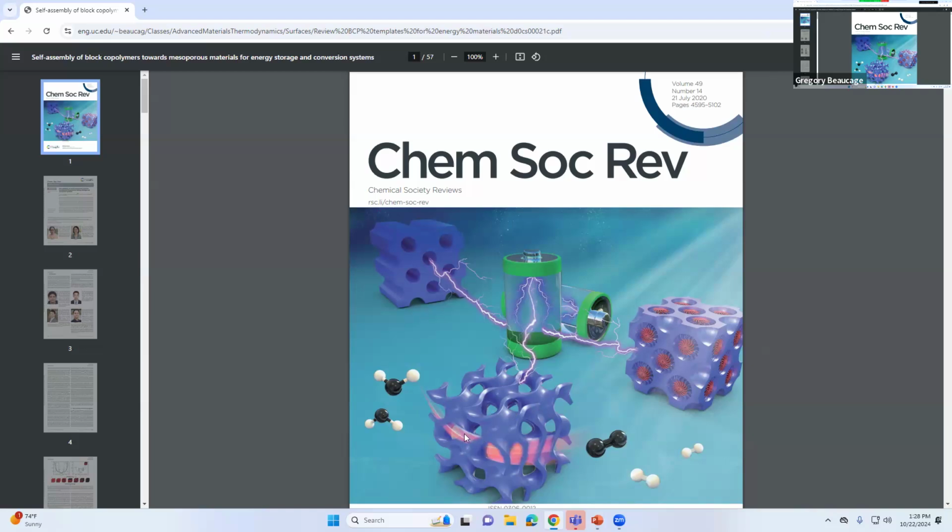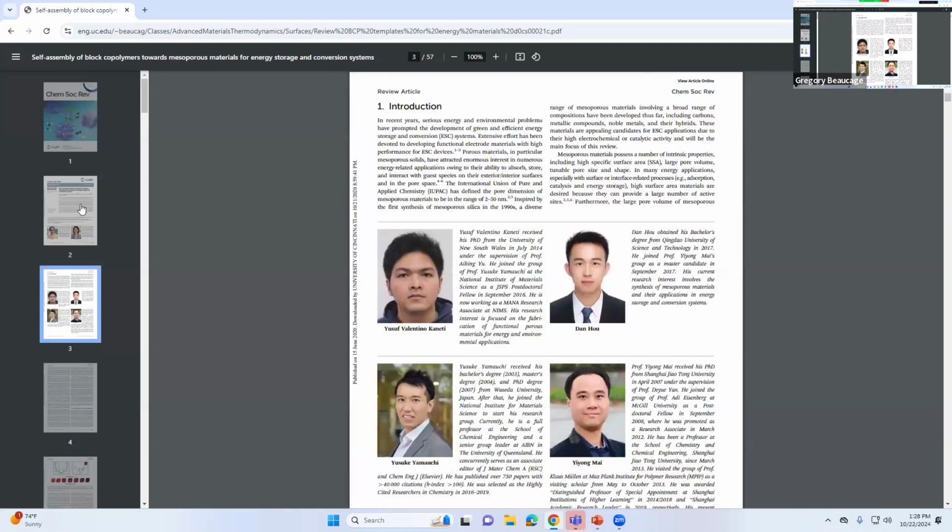One of the two polymers can be dissolved out and you can be left with pores. Or maybe one is hydrophilic and you can swell it with a sol-gel material that makes a ceramic in it. And then you can pyrolyze the whole thing and make the structure. There are papers about doing that.